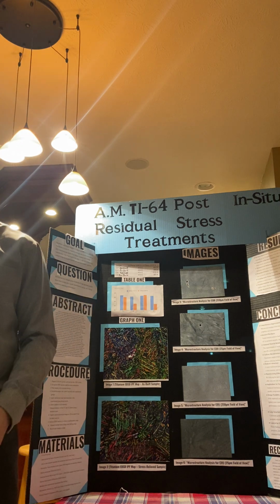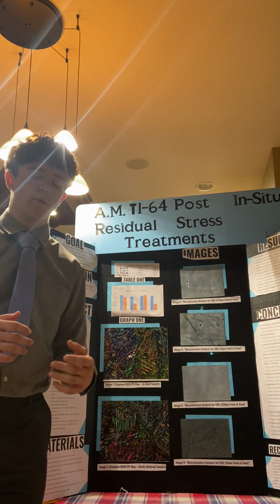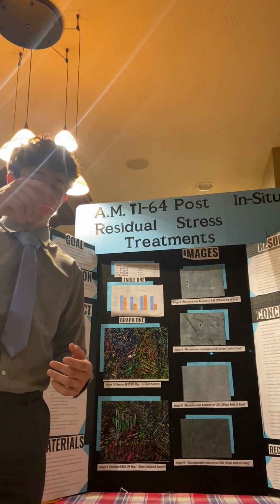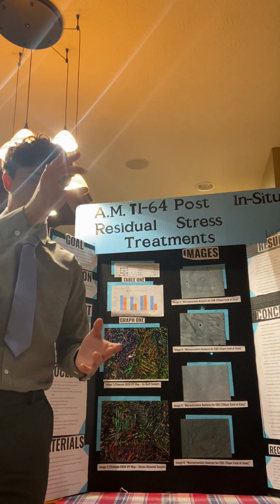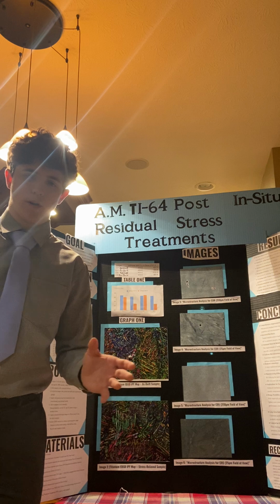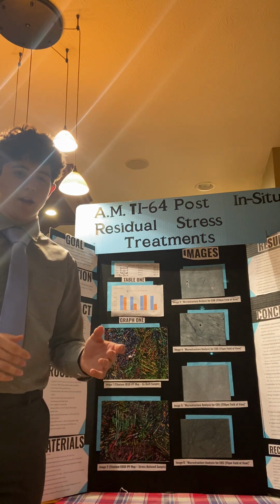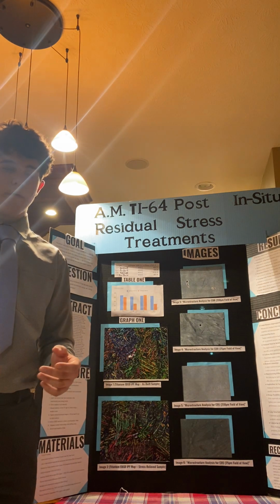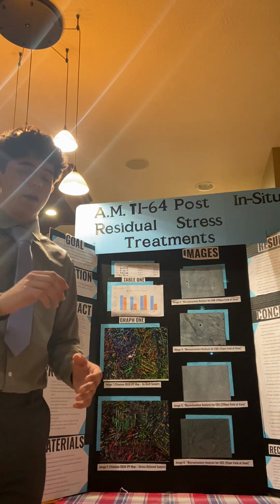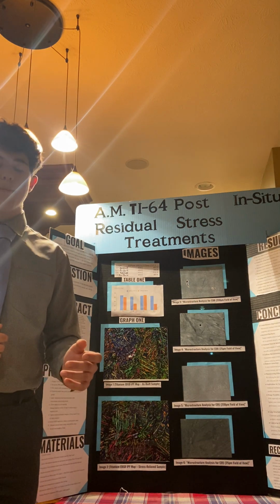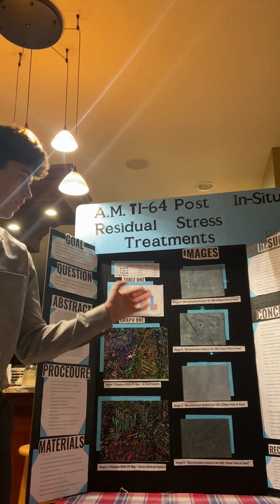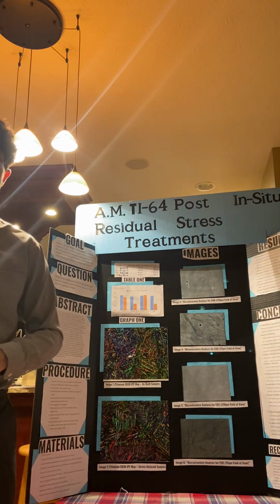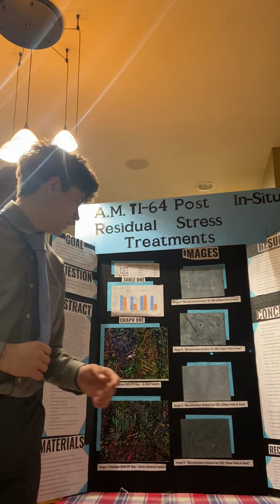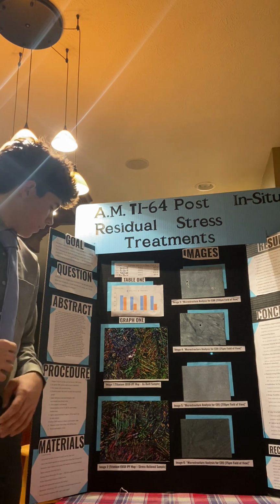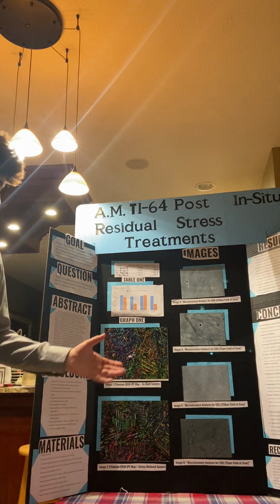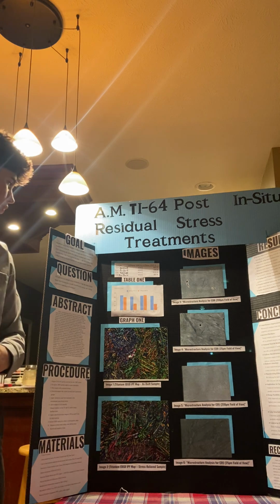We did it according to the Vickers hardness scale, and how that works is it's basically a diamond tip. It's like a pyramid, you can imagine, and it indents the material. With this project, it was 15 grams of force, and it measured the length, width, and depth of the indent. They calculate the hardness, and I did 10 indents per sample, and then averaged it to get the data that is presented here, and that is the hardness levels of it. And yeah, the hardness testing, and that was my overall procedure here.